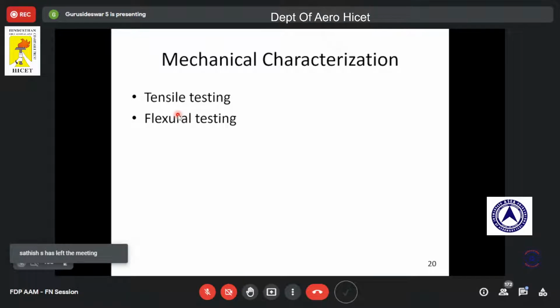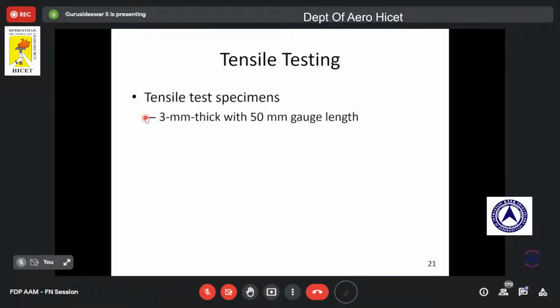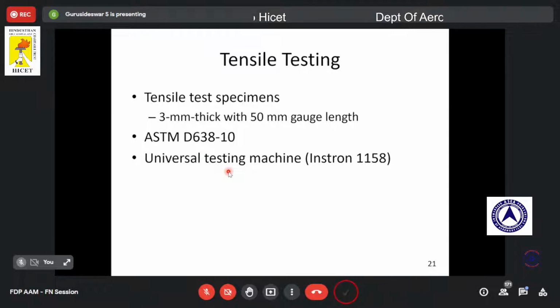Fine. So now let us focus on the mechanical characterization. So far we have discussed the microstructural characterization. Now let us come to the mechanical characterization of nanocomposites. How are we going to characterize the mechanical performance of nanocomposites? Using different techniques: tensile testing, flexural testing, impact testing, hardness, like that. I'm going to brief each testing one by one, and also mention the standard which we have used. For tensile testing, we used a dog bone sample as per ASTM D638. We have done the testing using a universal testing machine.